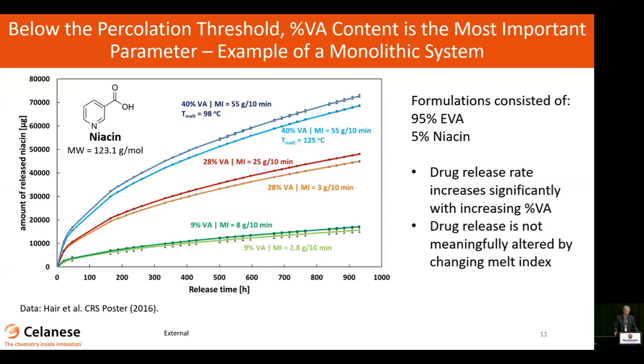So here's an old example that we did in our laboratory a number of years ago, where we just wanted to develop some very basic demonstration data on how both melt index and vinyl acetate content can affect drug release characteristics. So we took niacin, a simple, easy to handle model compound. We did extrusion and put it in at 5% by weight into EVA. If you look at this plot, you see there are 3 different colors of curves. We're showing the amount of drug release versus time. The green curves correspond to a 9% vinyl acetate copolymer, the red curves correspond to a 28% vinyl acetate copolymer, and the blue curves correspond to a 40% vinyl acetate copolymer.